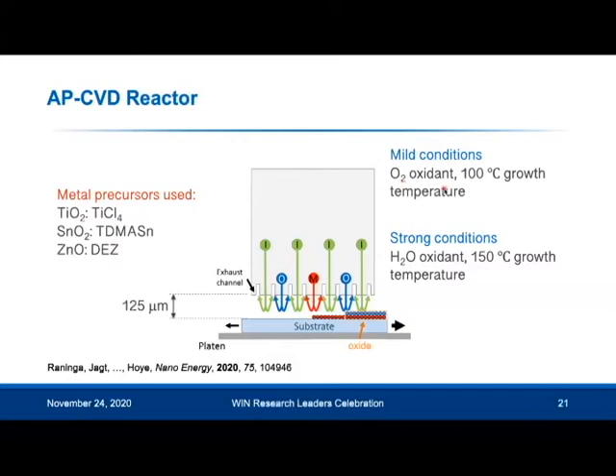I just want to emphasize that with ALD, I can't use oxygen gas. It's not reactive enough, but with CVD, I can. So this is something different with APCVD compared to ALD. And this oxidant is less reactive with the perovskite. I'm using a low deposition temperature of 100 degrees Celsius, which is within the range of temperatures that people have used with oxide buffer layers in the past.